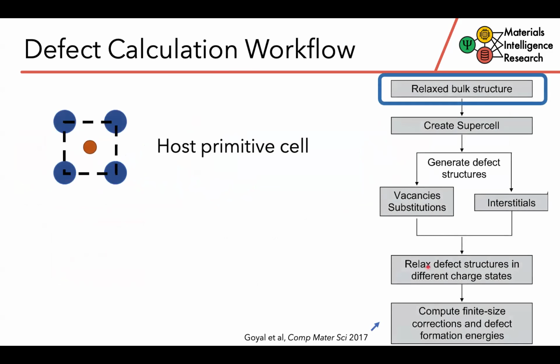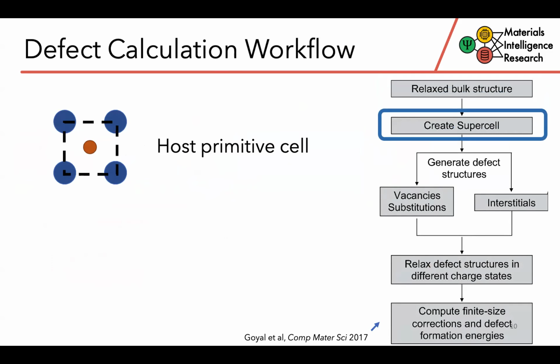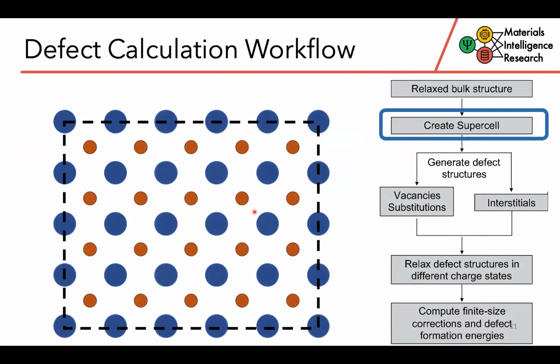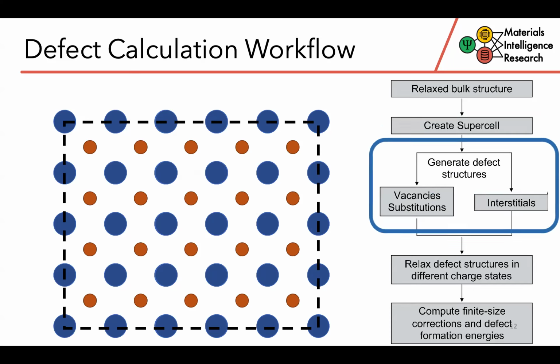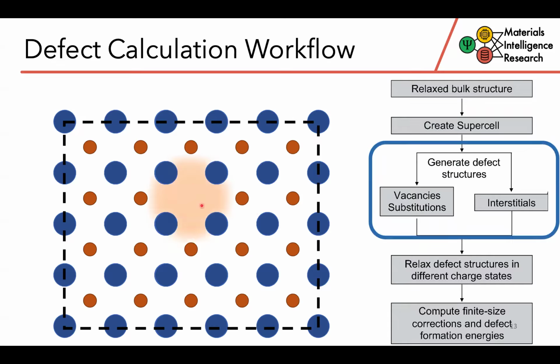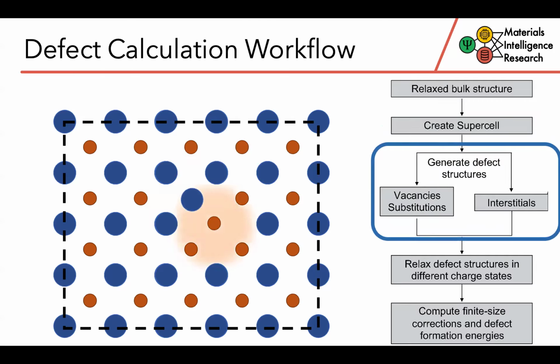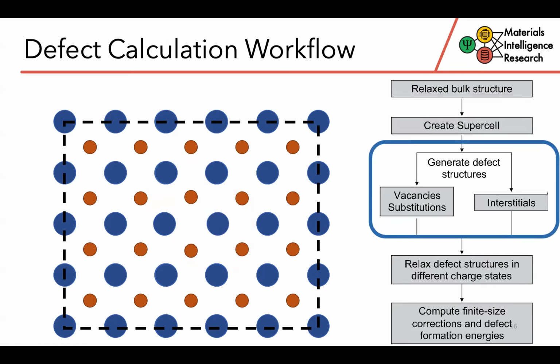Okay, so how do we actually go about calculating point defects? Well, the most common approach is the so-called supercell approach, where we start with the primitive structure of our host material. From this, we make a supercell, which ideally should be large enough to avoid significant defect-defect interactions in neighboring periodic images. With that, we then create the different types of defects that we want to calculate. So, for example, a vacancy we can create by just removing one atom like this. We could also do other types of defects, so substitutions or swapped anti-site pairs. We can also have interstitials, like an additional atom within the lattice of our material.